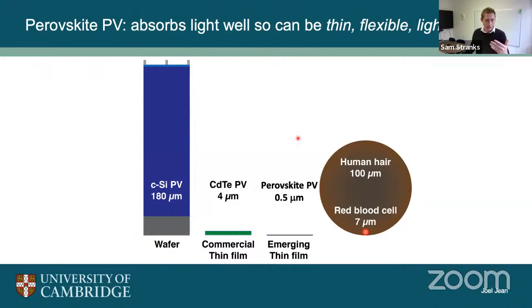And because, as I said, they can be processed on flexible substrates, we can make very, very thin cells, and they also absorb light really, really well. In fact, much, much better than silicon. So, for example, for a silicon cell, typically we need to have a thickness of something like 200 micrometers or close to 200 micrometers to absorb enough of the sunlight. A micrometer is a thousandth of a millimeter. So this is already quite thin.